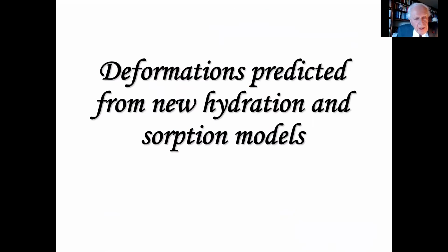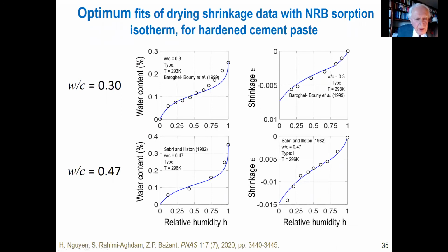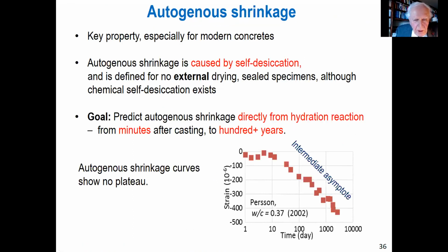All right, so next one needs to predict deformations. That includes shrinkage too. It has to do it from the hydration model and from the sorption isotherm and our NRB isotherm. So results are shown here for different water cement ratios, plotting water content percentage of the concrete volume or cement paste volume, depending on which data. So this is one water cement ratio, much higher water cement ratio. Recent data, not too old, from Baroghel-Bouny, data from Illston in London. All these are fitted and predicted with parameters which fit all the data on that model.